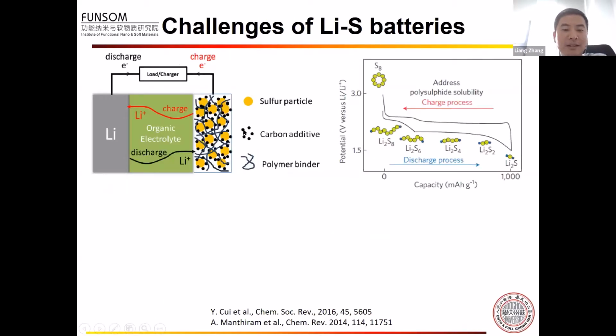So for typical lithium-sulfur batteries, sulfur is usually used as the cathode material, and lithium metal is used as the anode material. There are also the electrolyte, polymer binder and the carbon additive in the batteries. During the discharge process, because we start from elemental sulfur, the sulfur will first be reduced to high order polysulfide, and then to short order polysulfide, and then finally to lithium sulfide. During the charge process, the reaction path is reversed, which means the lithium sulfide is first converted to polysulfide and then to elemental sulfur.